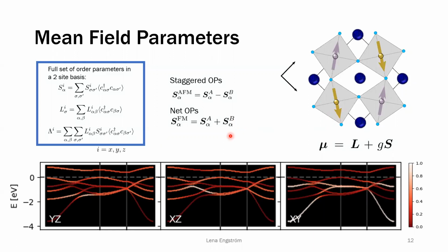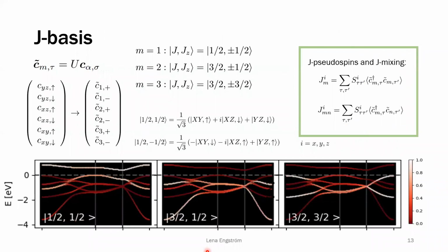Now, it physically makes sense to look at these magnetic order parameters. The only problem is that we have a strong spin-orbit coupling, which means that we should actually look at the eigenstates we get for the band structure. So this is the antiferromagnetic order. Since we have a gap, we can project the different orbitals onto this band structure and see that basically all bands are a mix of all these orbitals. So they're not really great states to describe processes close to the Fermi surface. So what we want to do instead is rewrite the whole Hamiltonian, or at least the order parameters, into a new basis that is more appropriate.